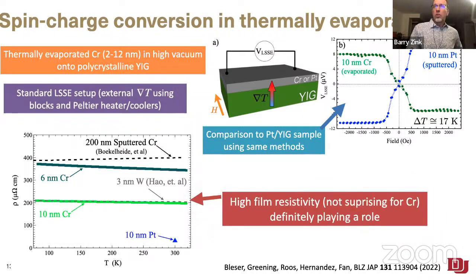And so the first thing that you think is, well, chromium is going to have a pretty bad electrical conductivity compared to platinum. This is what you normally would expect. This is the data for our actual films, several of them, or two of them here. So 6 nanometer chromium and then 10 nanometers of chromium, both this evaporated stuff. What you notice is that the resistivity is really very high. So part of what is happening in these large spin Seebeck signals is certainly just that there's less shunting of the charge that you build up with the inverse spin Seebeck effect, right? So we'll be able to understand that part. But I'll just note that one of the other common negative spin Hall materials is quite thin tungsten. And as a point of reference, our chromium has nearly the same resistance as a thin tungsten film does. So it's in that ballpark.